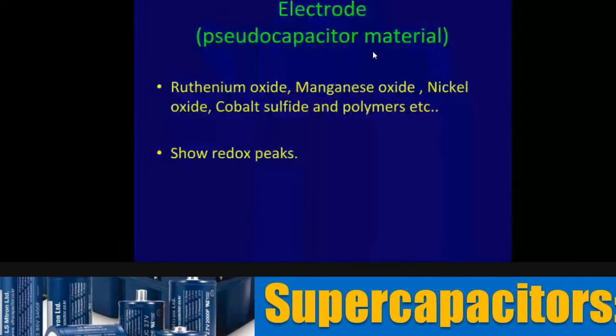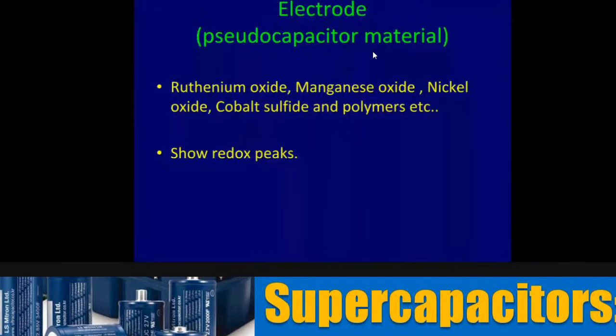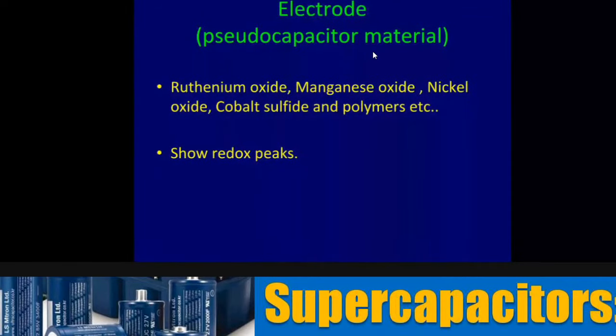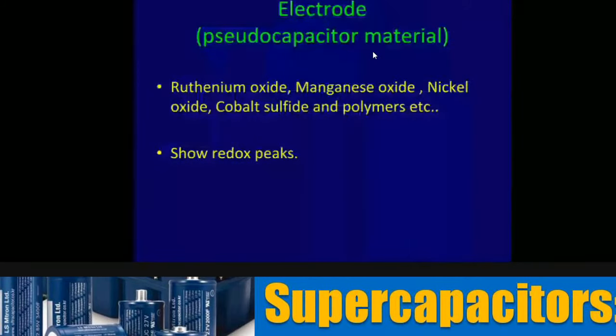So the major reason for the choice of transition metal ions, or transition metal oxides, is that these metals can undergo more than one oxidation reduction process, thereby enhancing the charge storage capacity of a single ion. And these show redox peaks, reduction oxidation peaks. Today, people are working on transition metal sulfides and some of the polymers where the problems associated with bulging and shrinking are reduced to a larger extent.